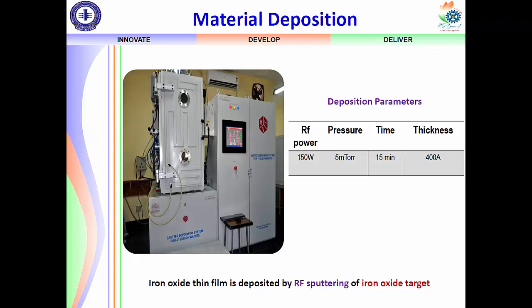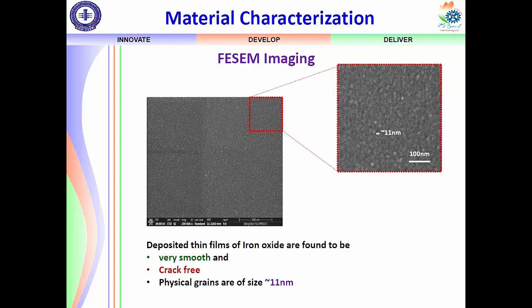After material deposition comes characterization. This is the morphology of the sputtered film. You need a smaller grain size to have larger sensitivity. More grain boundaries give more sensitivity because you have more sensing sites. If the grain size is larger, you have fewer grain boundaries, which gives less sensitivity. That is why we characterize the morphology.